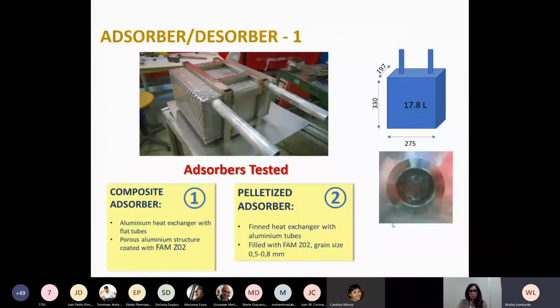So I will talk about the adsorber. We designed and sized this component under constraints provided by an industrial company, constraints of a real component. We designed the adsorber sizing for 25% of the full capacity. And we tested two different types of absorbers. The first one is a composite adsorber, characterized by an aluminum heat exchanger with flat tubes, with a coating of FAM Z02. And the second one is a pelletized adsorber with a finned heat exchanger with aluminum tubes filled with grains of the same adsorbent material.